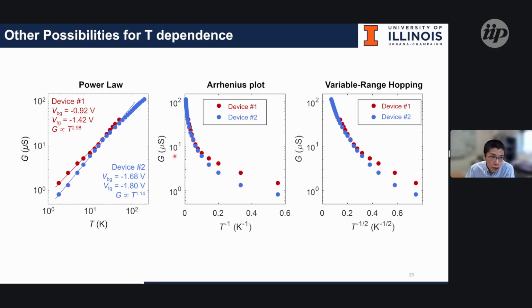We also plot the conductivity as an Arrhenius plot, which is the 1/T behavior, as well as you might argue that it could be a variable range hopping situation. But it doesn't fit for either situation, Arrhenius or variable range hopping. This is barely because at low temperature range, it doesn't fit with the single linear line behavior. But in the power law plot, you can see that at low temperature, it fits very well with linear behavior in such a dual log plot. So this actually excludes both Arrhenius activation and variable range hopping.